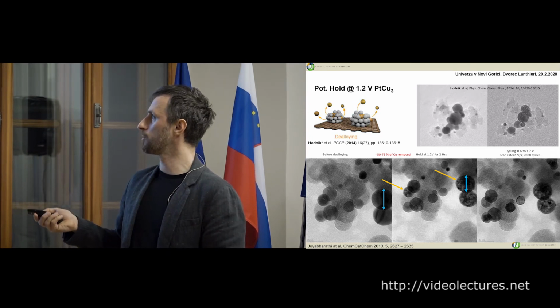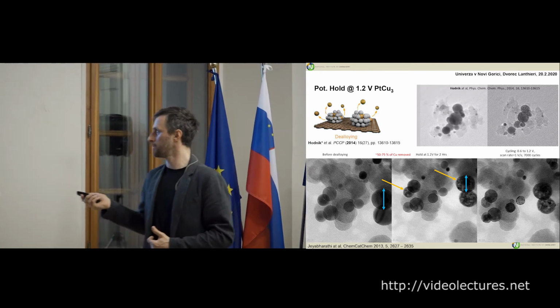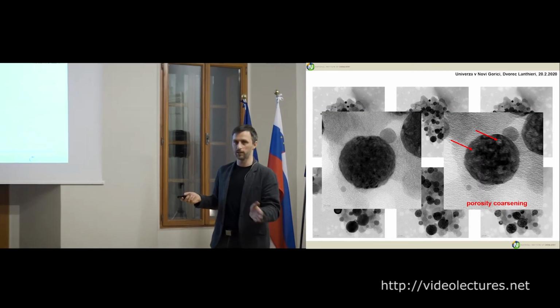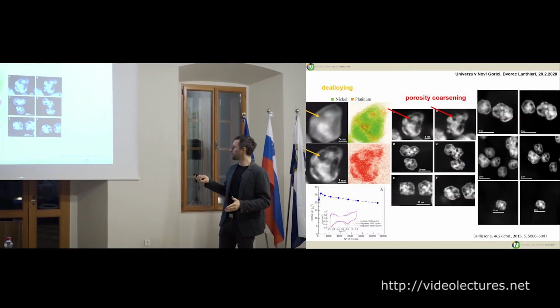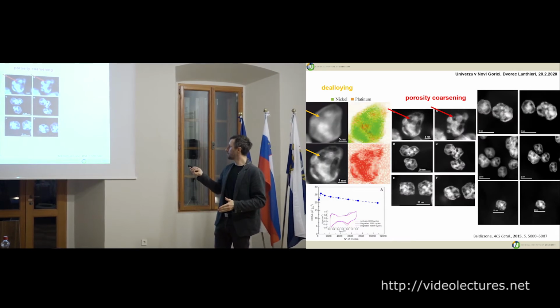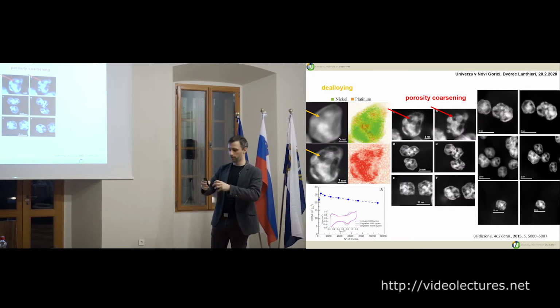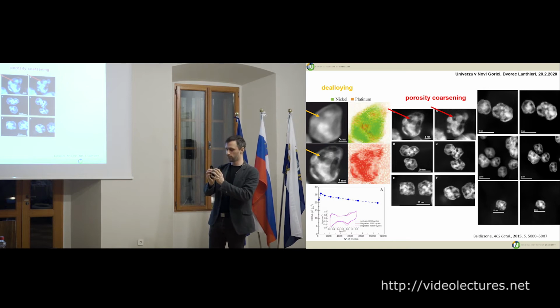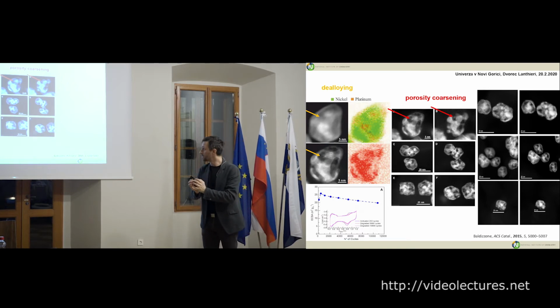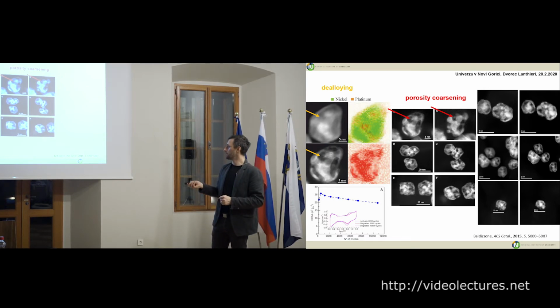This was interesting because we did this study when I was in Germany. We have platinum nickel, nickel goes out, but when you continue to cycle, you can see that the pores grow and in the end they tend to make a smaller surface. And this is happening at relatively mild conditions, which I think is really important. This is happening because the surfaces are actually touching each other, and then the surface diffusion can occur, to minimize the energy.